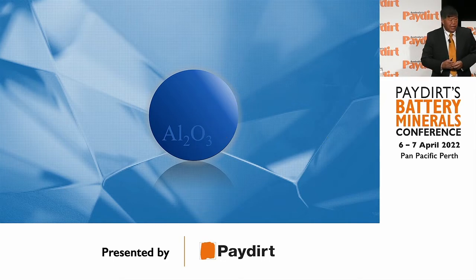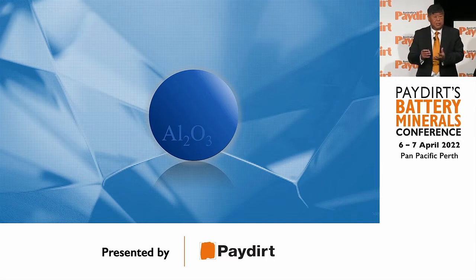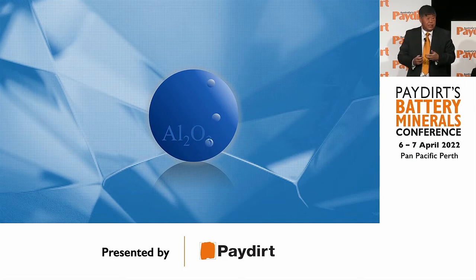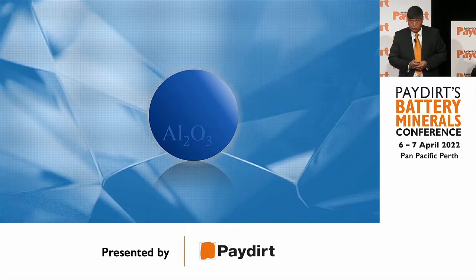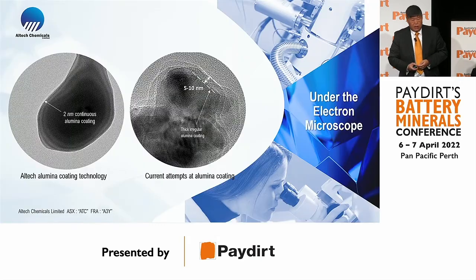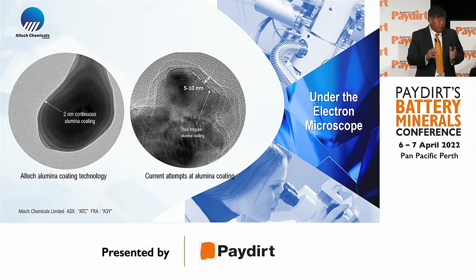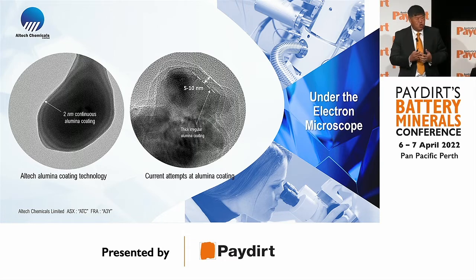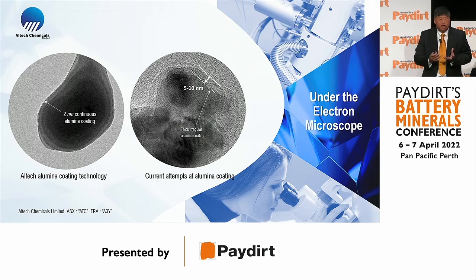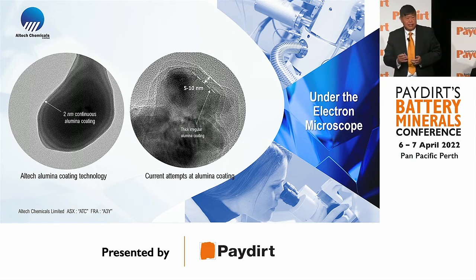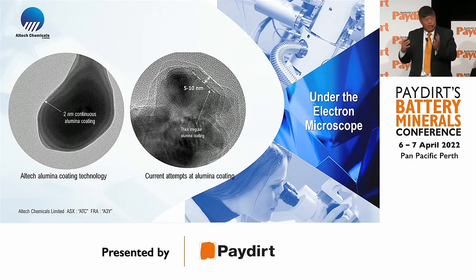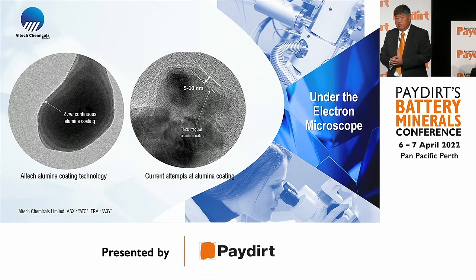I mentioned the hydrofluoric ions. There's a lot of research that shows that the alumina layer absorbs the hydrofluoric ions and turns them into an inert material, so it doesn't impact the future performance of the battery. So quite a lot of benefits from this alumina coating. This is some of the material under a microscope. You can see on the left-hand side, the white layer around it is our 2 nanometer alumina coating. You can see how uniform that is. On the right-hand side is what the industry is trying to do. They're very thick, irregular layers around that graphite material.